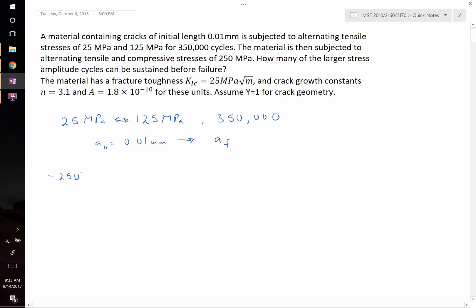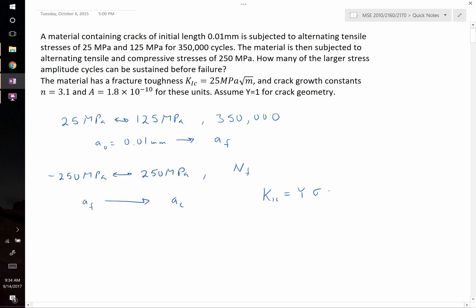Then we go from negative 250 megapascals to positive 250 megapascals, cycling between tension and compression at 250 megapascals. The question asks how many of these cycles — N_sub_F — can be sustained until failure. Before answering that, we need to know how big the crack gets, starting at A_F and growing until it reaches A_C, the critical crack length. We solve for A_C using the fracture toughness equation: K1C equals Y times sigma times the square root of pi times the critical crack length. Then we plug that into the crack growth equation to find the number of cycles until failure.